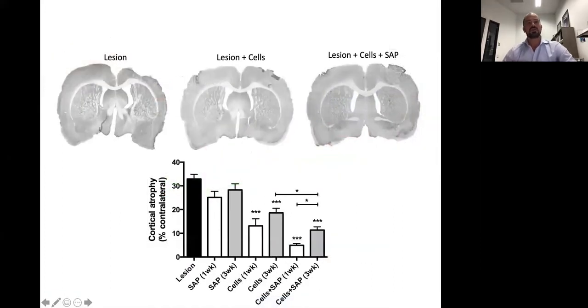So then we spent a bit of time looking at why that's occurring, and you can see that in these brain slices here. But basically the reason that that's occurring is because we're regenerating cortical tissue. So you can see the lesioned animal, there's a lot of cortical atrophy. If we put in the peptide material, either early or late intervention alone, there's actually no statistical difference whatsoever. So the material on its own is doing nothing. It needs to be a combination of both.